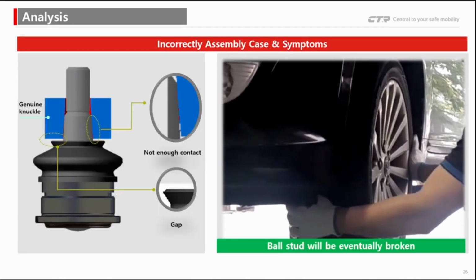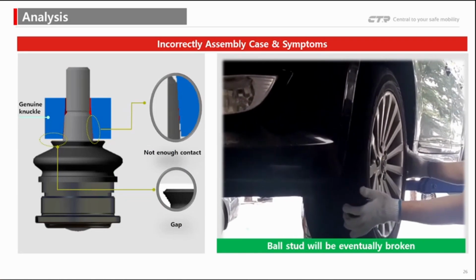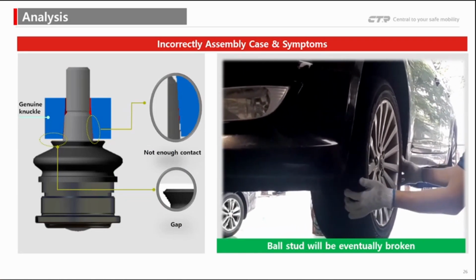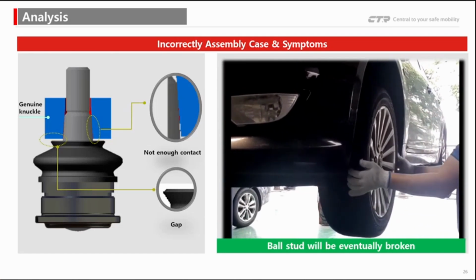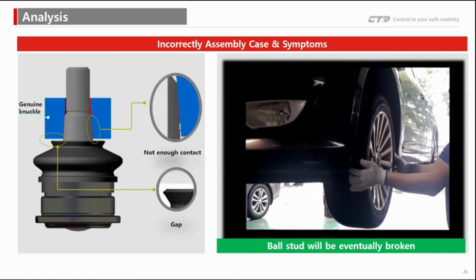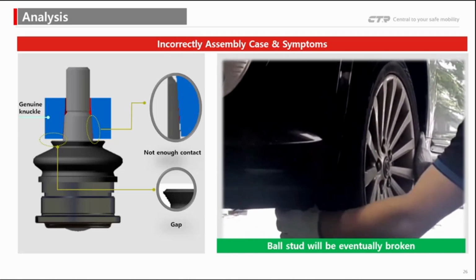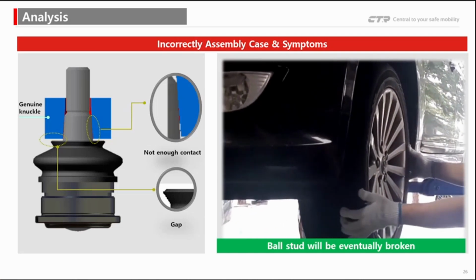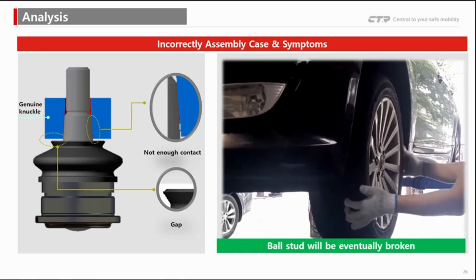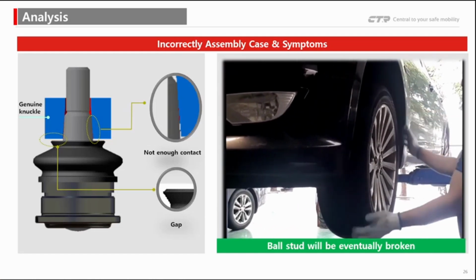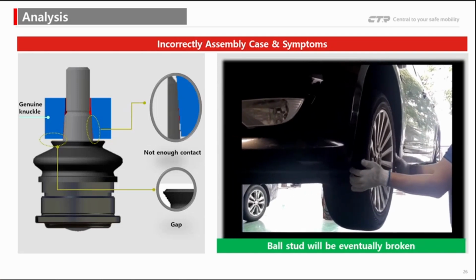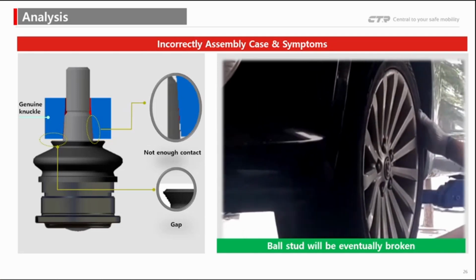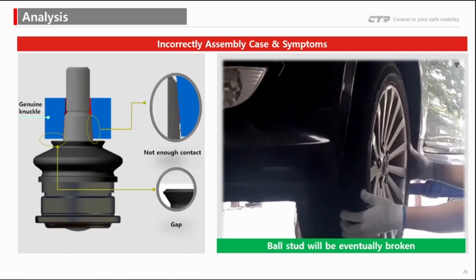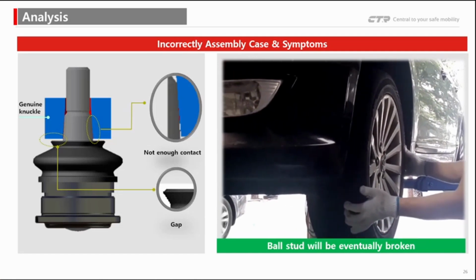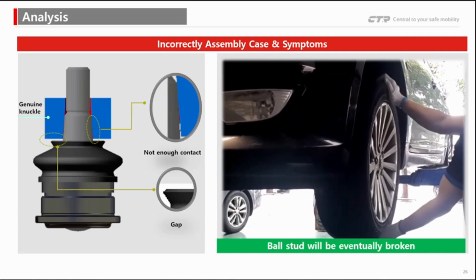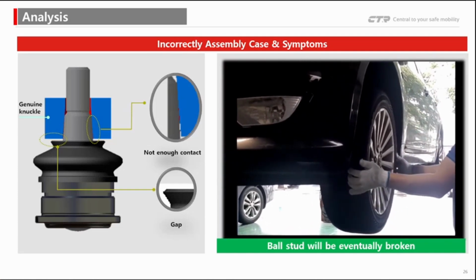This slide highlights the risk of installing a counterfeit ball joint into the vehicle. On the left, you can see a cross-section diagram showing what happens when a fake ball joint, which has a non-standard taper angle, is inserted into the genuine knuckle. As a result, the stud doesn't fully sit in the knuckle. There is an insufficient contact area. A gap remains, which leads to looseness and instability. On the right, we have included a video that shows the actual symptoms observed when a fake part is installed.